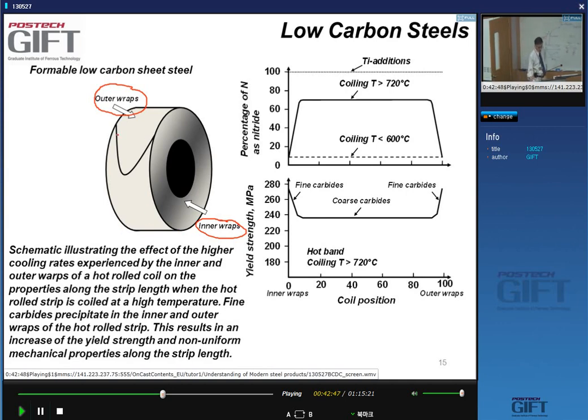And they also end up being at lower temperatures, yes? And the reason is the outer wraps cool faster because they're exposed to the ambient temperature, so they're colder. And the inner wraps are cooler because when we roll the strip, it goes on a mandrel, which is cold, right? A mandrel is a cylindrical piece of steel on which you wrap the material. That's cold, so it cools down quickly.